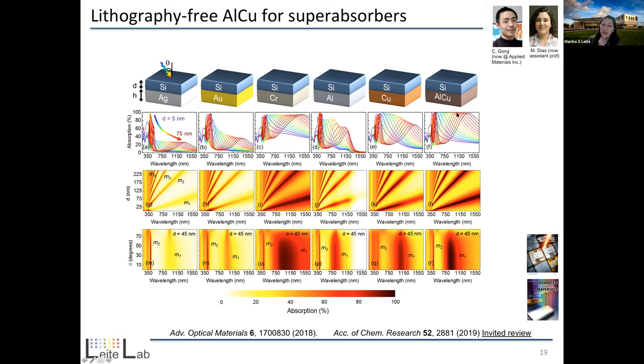And we could obtain a multi-wavelength type of response. Basically, again, depending on the thickness of the slab of silicon, we could choose or select exactly in which wavelength we wanted this absorption to occur. And then we saw that here we could resolve all the optical modes. That's what M1, 2, 3, 4 correspond to, as a function, again, of the thickness of the silicon layer.